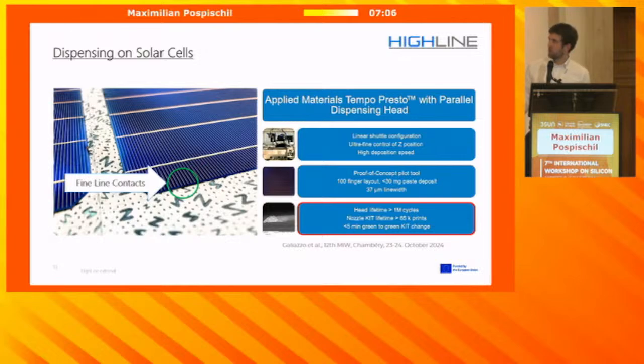And what we achieved here, you see this here, our head lifetime. This is from Marco. He published this two weeks ago in Chambéry, and now we are at 1.5 million cycles already. The nozzle kit lifetime with this heterojunction silver paste here was 65,000 prints. Has to grow, of course, some more. And then the last thing, 5 minute green-to-green kit change. This is a very important parameter for production. So we are happy to have this collaboration and making progress, and that's the way to really put this process from our facilities, very small, in Freiburg to the market.